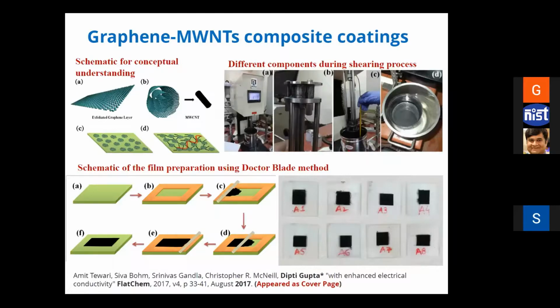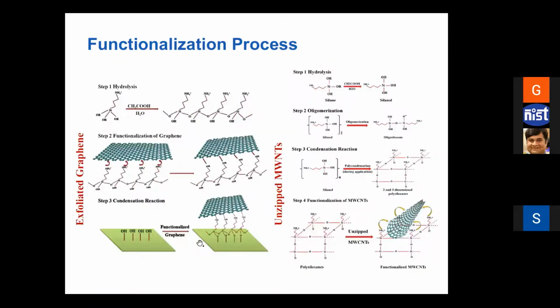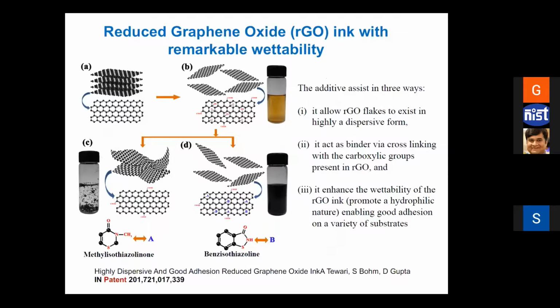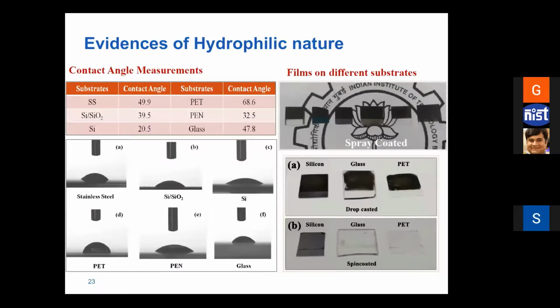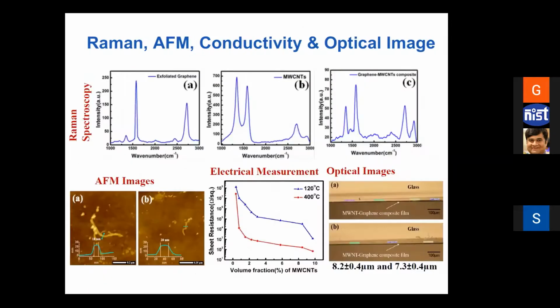And these are a few ways in which we have come up with different composite coatings, basically exfoliations, and tested them on different surfaces. And these are a few functionalization processes of the ink. Again, I'll not go into much detail because this is all synthesis of the ink material. And then for testing, we rigorously tested all the ink material with Raman spectroscopy, AFM images, electrical measurement, and optical images, because all of these are required to understand your ink material and how it coats on different surfaces.